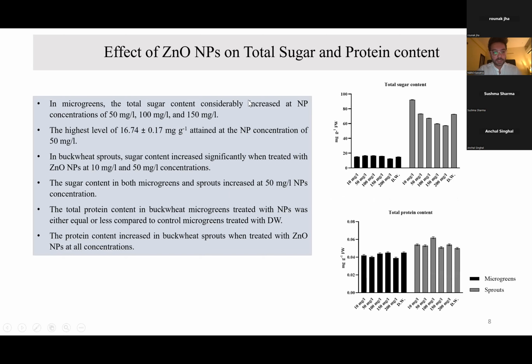After this, the effect of zinc oxide nanoparticles on the sugar content and protein content. Talking about microgreens first, the total sugar content considerably increased at concentrations of 50, 100, and 150 mg per liter, with the highest content of 16.74 mg per gram that was attained at a concentration of 50 mg per liter. In buckwheat sprouts, the sugar content increased significantly when it was treated with 10 and 50 mg per liter concentrations. The total protein content in buckwheat microgreens treated with nanoparticles was either equal or less when compared to control microgreens, whereas in buckwheat sprouts, the protein content increased with the zinc oxide nanoparticles at all of the concentrations.